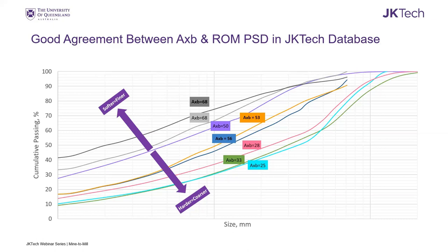The full run of mine particle size distributions don't get to be measured very often at sites, only when process integration projects are conducted. This actually is the coarse end taken from image analysis, and the fine end from belt cuts of the primary crusher product, since primary crushers do not generate too many fines. It's just dealing with the top size.